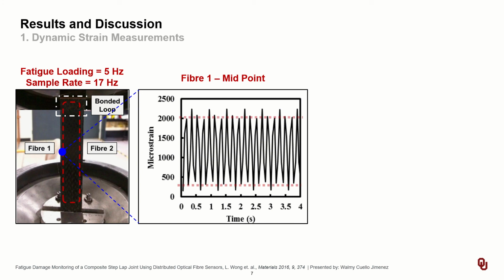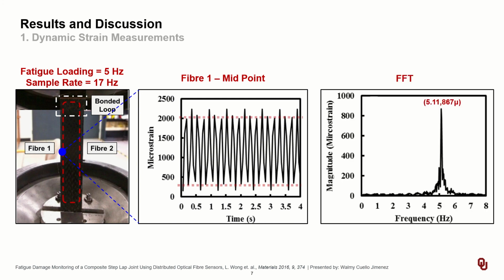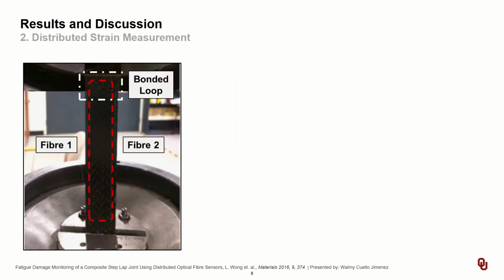way to 2000 microstrains. And by employing an FFT, a cyclic frequency of 5.11 Hz and a maximum microstrain amplitude of around 870 microstrains were determined. Interestingly enough, results indicate that the strain measured by the distributed optical fiber system corresponds to the fatigue loading profile.